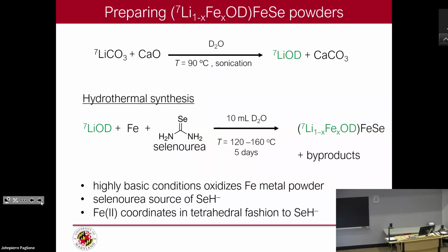The way we made this compound is we made an isotopically pure compound. We made all lithium-7, all deuterium, because we do neutron scattering. Lithium-6 is a high neutron absorber, and hydrogen is a horrible incoherent neutron scatterer. Sometimes it's okay. I mean, you can still get coherent scattering from hydrogen, and you can solve crystal structure that way. But deuterium is really nice when it comes to coherent scattering. So we did this chemistry all in D2O.